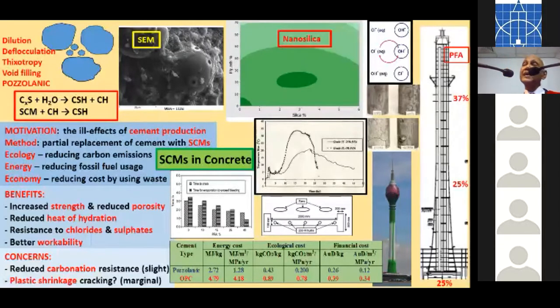That is because at 400 degrees centigrade, you have dissociation of calcium hydroxide. When it cools back to room temperature, it is rehydrated by atmospheric moisture, and then the rehydration causes expansion that causes cracking. Now, this is the same thing here with 0% PFA, but even with 10% PFA, you can prevent this cracking of the cement after exposure to temperatures in excess of 400 degrees centigrade.